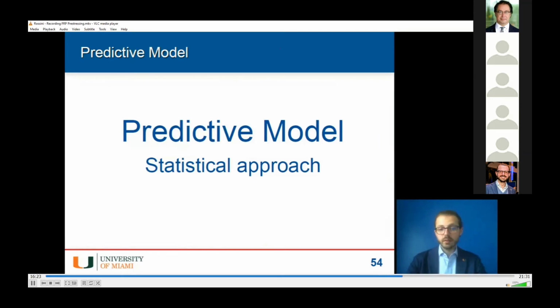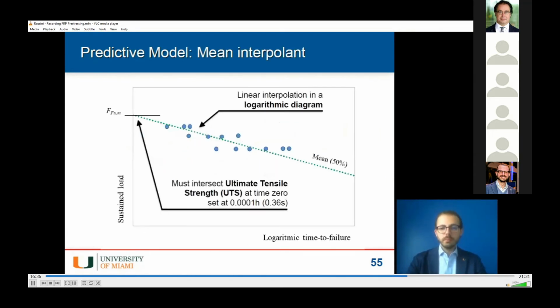Because in addition to a lack of experimental data, we noticed a lack of conceptual background in order to interpret this data. We know that we can plot time-to-failure points in a logarithmic diagram. What is crucial in this slide is to notice that our interpolant line must intersect the ultimate tensile strength of our material at time 0. Otherwise, our modeling is not consistent. Because if you think about it, a tensile test is nothing but a very short pre-rupture test.